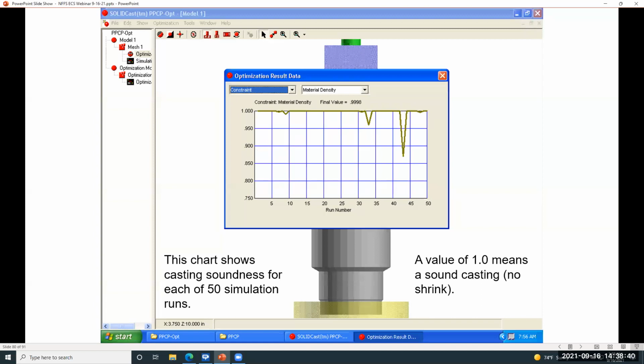This shows a chart of how the soundness varied. That is the shrink factor through those. Our final value comes out with a value of 0.9998, which actually is not our value of 1. But when we're doing optimization, we can allow what I call wiggle room. It's called a percentage of a constraint violation. We allowed it to vary up to 0.05%, and that would still be acceptable, and we're well within that range.